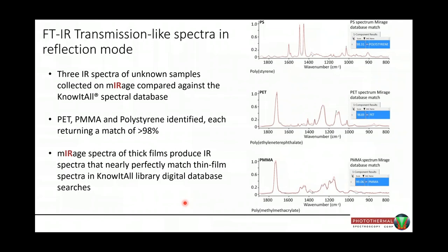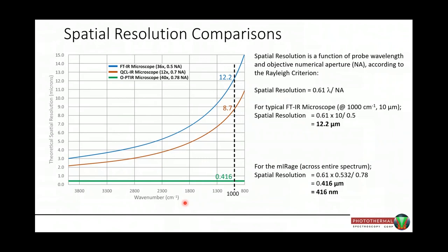If we compare spatial resolutions between FTIR microscopes, quantum cascade laser microscopes, and OPTIR microscope, you can see that the spatial resolution changes as a function of wavelength. It depends also on the numerical aperture of the objective. But in general, you get consistent spatial resolution up to about 20 times better across the whole mid-infrared range compared to conventional FTIR and QCL IR microscope systems. In this case, with a 532 laser, it works out to be 416 nanometer spatial resolution.